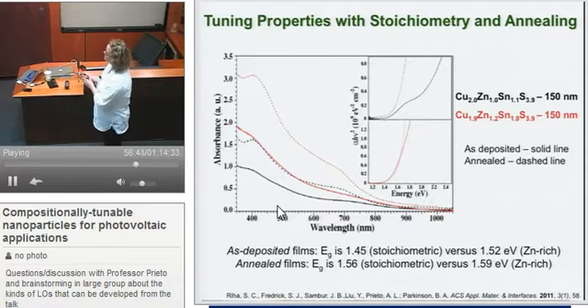Notice that I don't use a lot of significant figures for composition, for all the reasons that Ray mentioned. We do use standards with our EDS, but even those have composition ranges, and so people who show 3 and 4 significant figures for EDS haven't thought about limits of sensitivity for that technique.